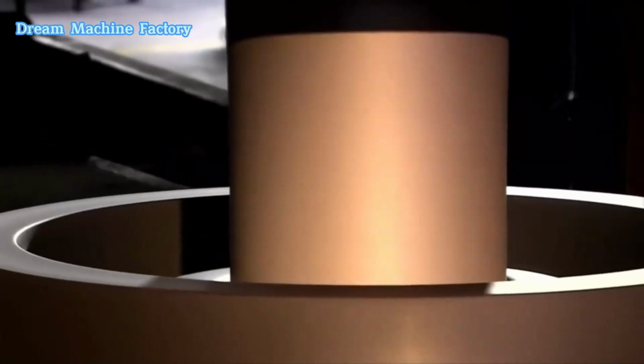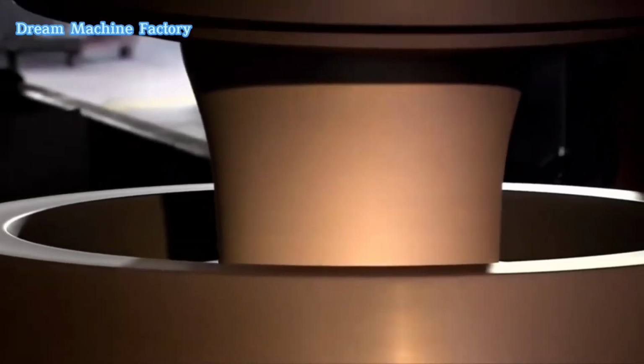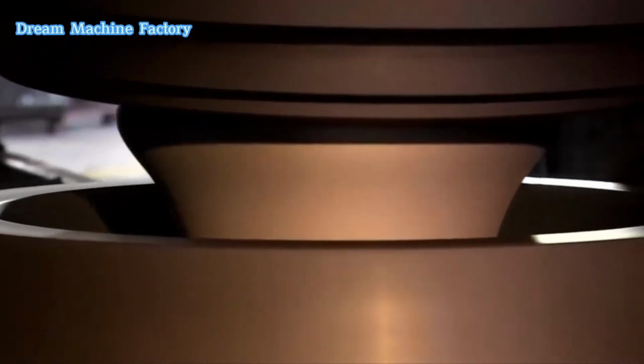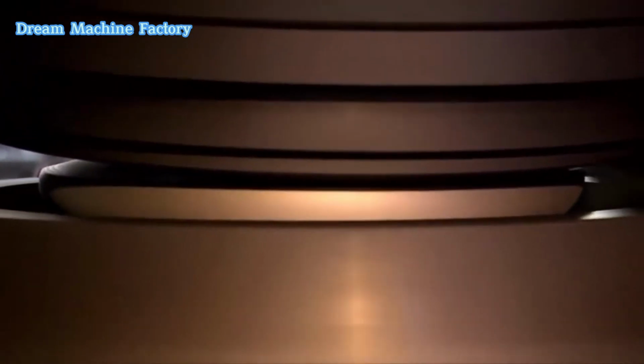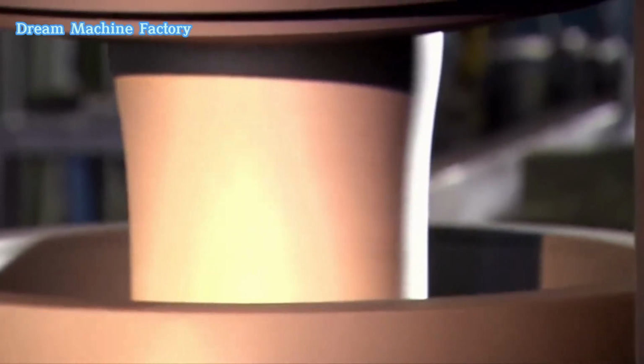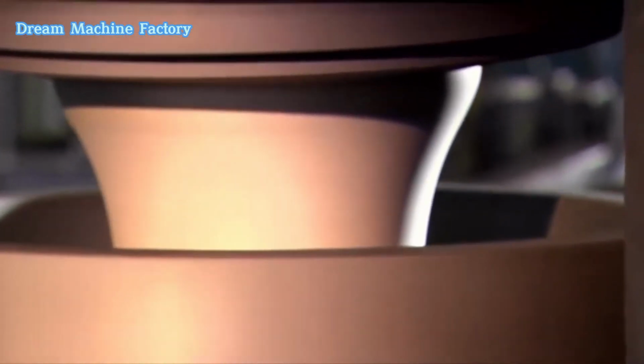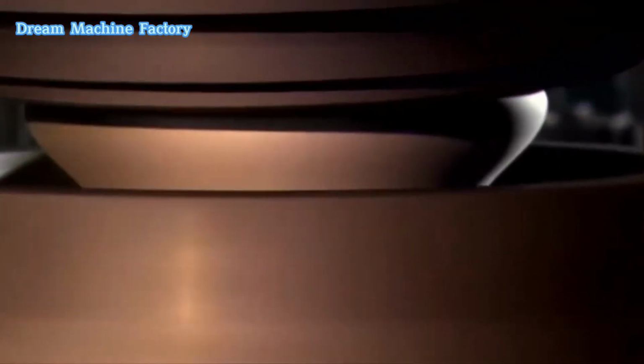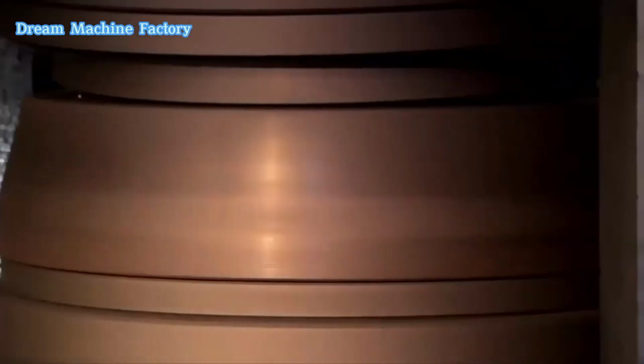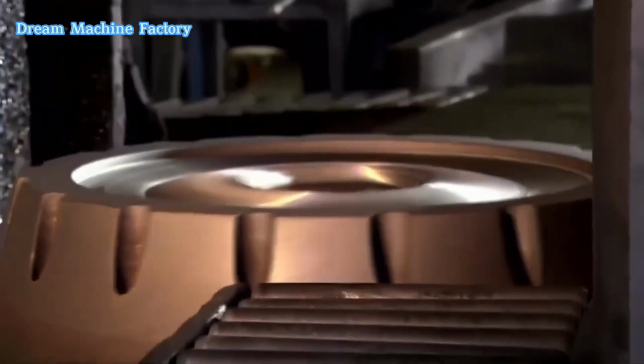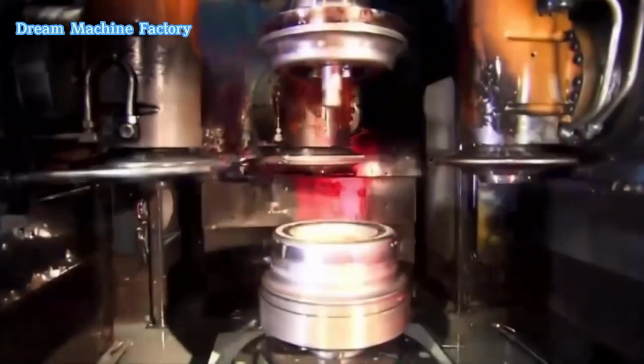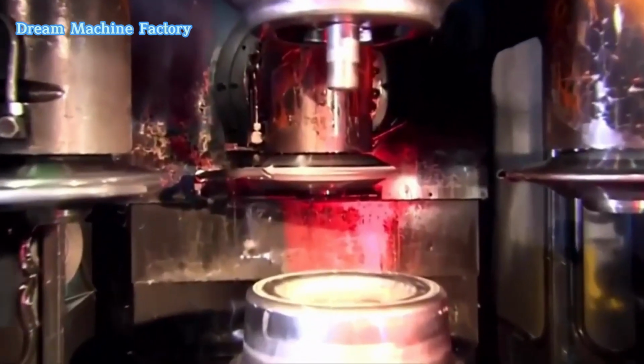Once heated, the softened aluminum blank is transferred to a rotary forging press. This press exerts extreme pressure, typically around 4,000 tons, to shape the aluminum into a disc. This process not only reshapes the metal, but also alters its molecular structure, making it denser and stronger. The forging process aligns the grain structure of the aluminum, significantly improving its resistance to impact and stress compared to cast wheels. The result is a lightweight yet highly durable wheel blank.